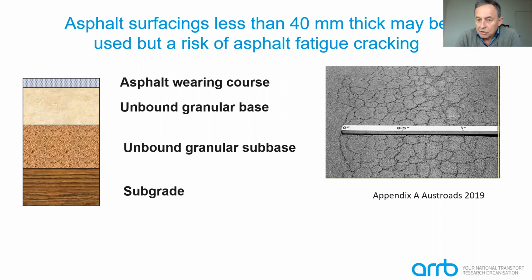So if you do use this chart, there's no consideration of the fatigue of the asphalt layers, and there's a risk that you might get fatigue cracking. Some designers might attempt to reduce the risk of that happening by using polymer modified binders in the asphalt, which have higher fatigue lives.